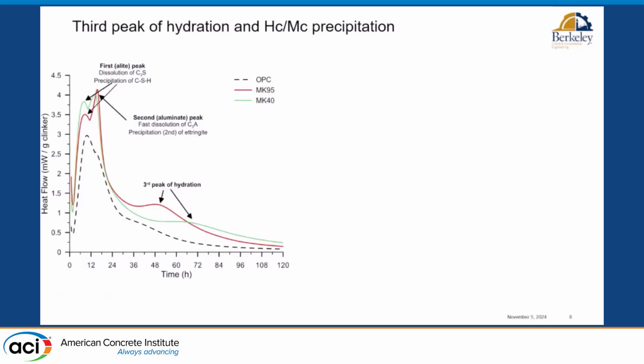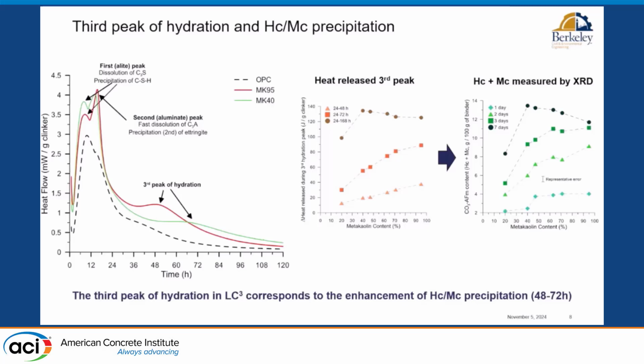We went even further in trying to understand this process, and we were actually able to identify a kinetic feature that we observe in the calorimetry curves of LC3 cements that relates to the precipitation of hemi and monocarboaluminate. So you remember that we say hemi and monocarboaluminate occur in every cement that contains carbonate, but we have more in LC3. And something that we observe in LC3 cements is this hump here. We also observe it in OPC, but in LC3 it's bigger. So we were wondering, well, what is that? And by comparing the heat release on this third peak of hydration, if we count as first the alite dissolution, right? Not the dissolution peak that is before.